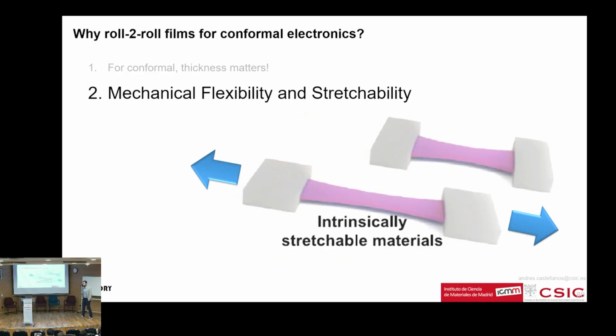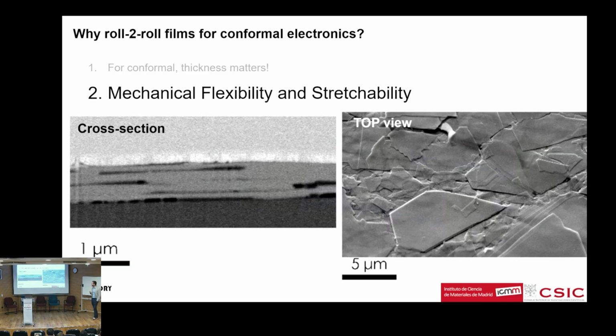The second thing is that this kind of conformal electronics usually has to be strong against mechanical deformations. Stretchability, especially, is a difficult one. Two-dimensional materials are inherently really sturdy against mechanical deformations. Single crystals can survive very big mechanical deformations. But also, these films are, as I said, a network of interconnected flakes. If you take a look at the cross-section or top view SEM, you see the flakes, a patchy kind of surface.